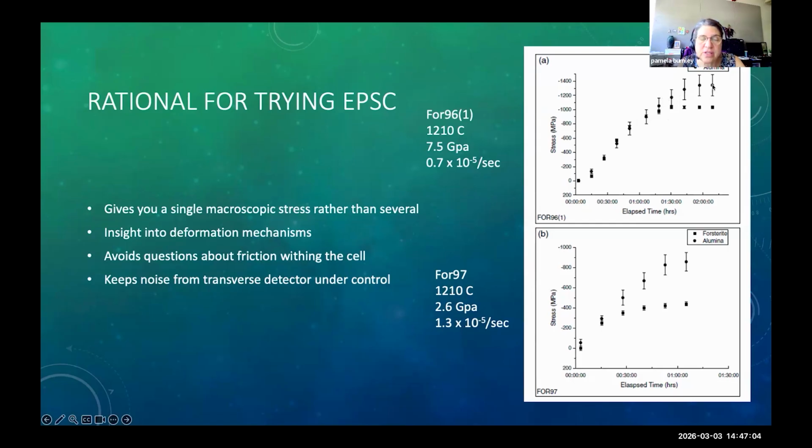get to higher stresses. So there are friction things going on inside your cell, which make it more desirable to get stress out of your sample than some other part of the cell. So this is just the same thing at a different condition. Early on, the piston and the sample agree, but as the sample yields, the piston records increasing differential stress.